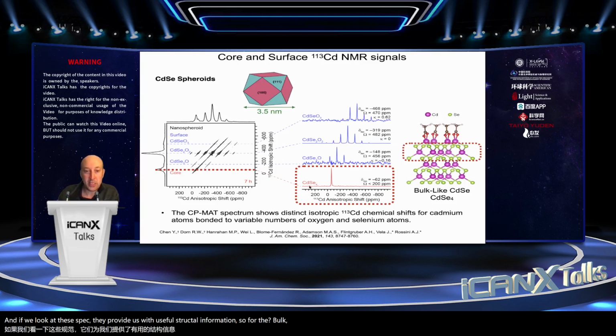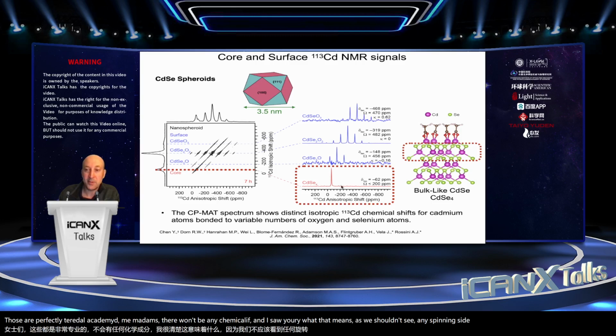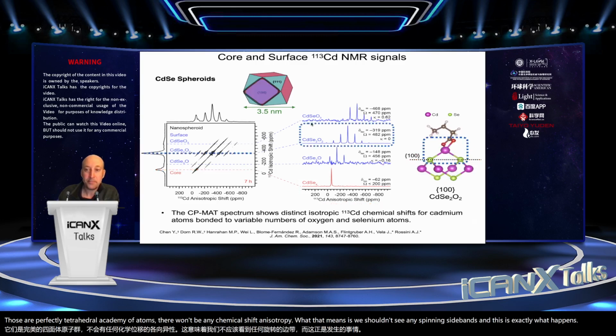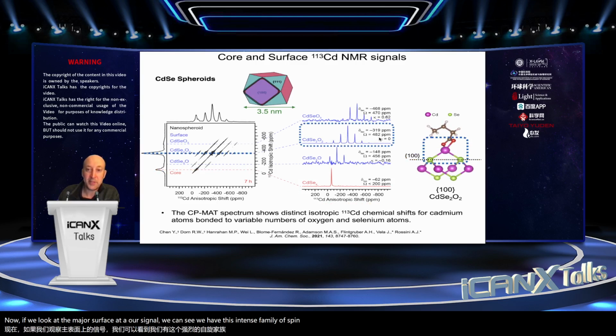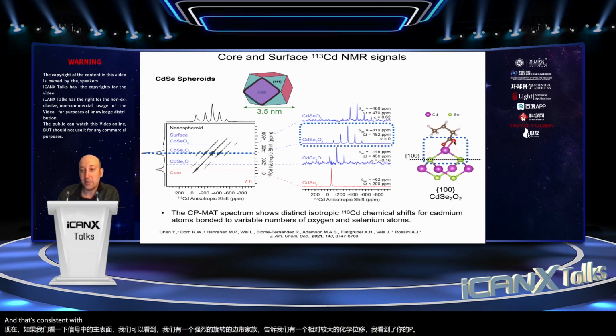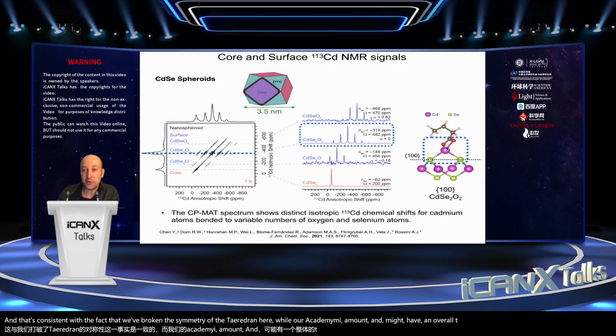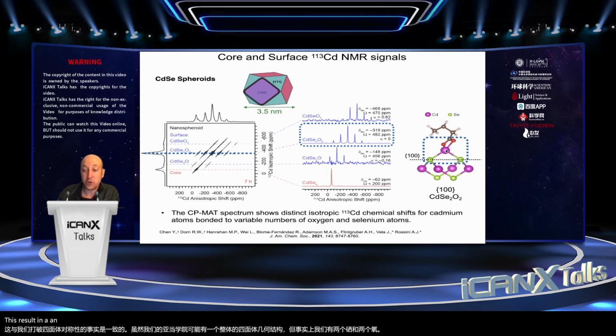So for the bulk signal, we know this must be cadmium that's coordinated by 4 selenium atoms. Those are perfectly tetrahedral cadmium atoms. There won't be any chemical shift anisotropy. What that means is we shouldn't see any spinning sidebands, and this is exactly what happens. Now, if we look at the major surface NMR signal, we can see we have this intense family of spinning sidebands. That tells us there's a relatively large chemical shift anisotropy, and that's consistent with the fact that we've broken the symmetry of the tetrahedron here. While our cadmium atom might have an overall tetrahedral geometry, the fact that we have 2 seleniums and 2 oxygens, this results in an anisotropic local cadmium environment, and that's reflected in the chemical shift anisotropy.